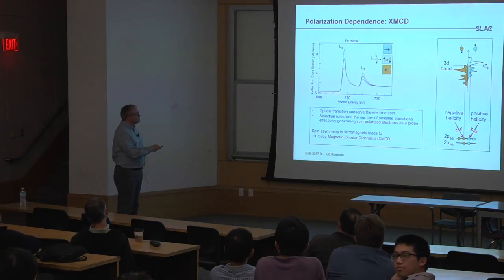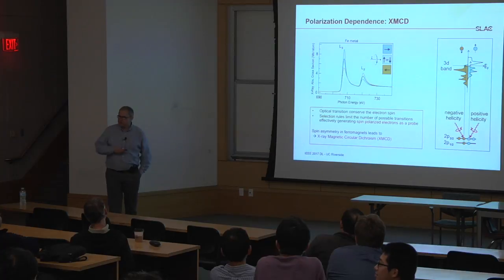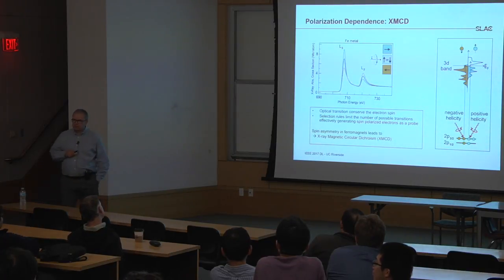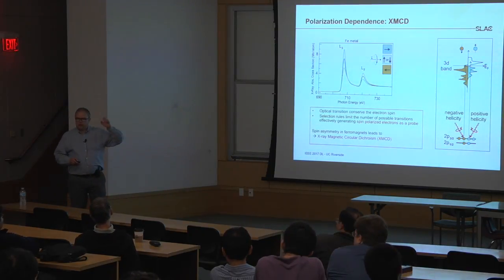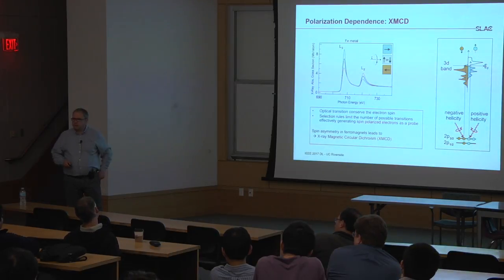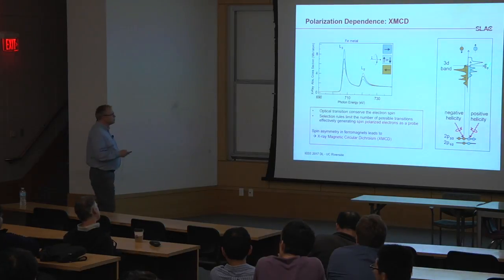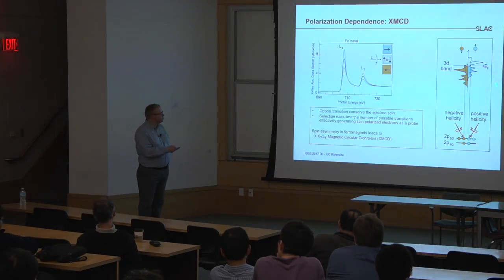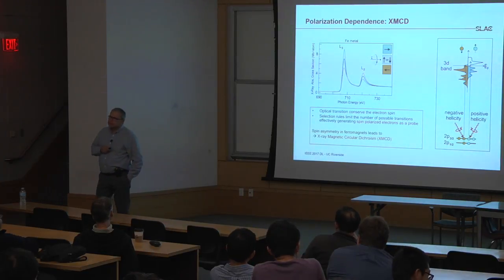No, so you're right. So maybe that graph is not so good. No, it's the total density of states that you would see, at EF and above, because you only have a certain energy resolution, so you're actually always integrating over a range. It's a convolution, yeah. Typically with the energy resolution that you have, you would probably get a window from here to here. I should actually put an energy scale on there so that it's easier to explain. That's actually a good point.